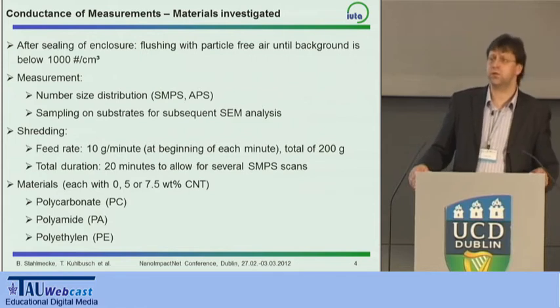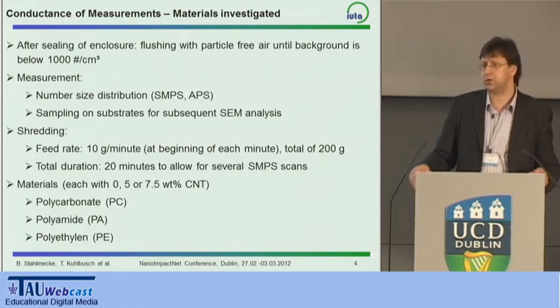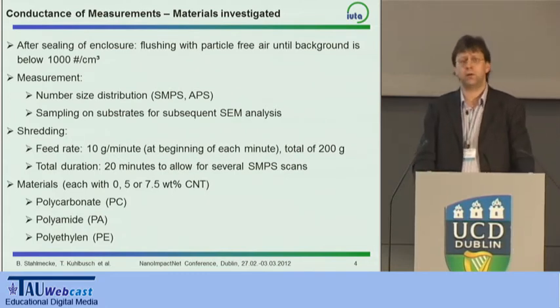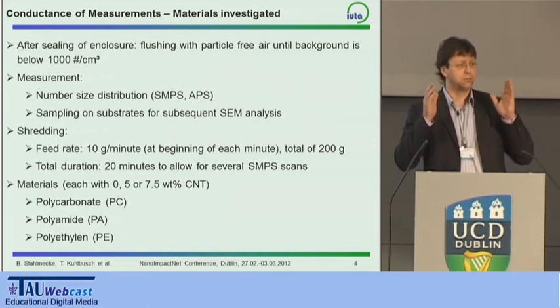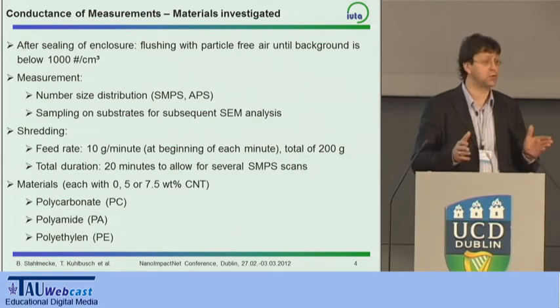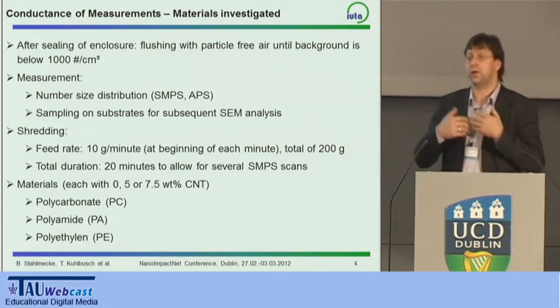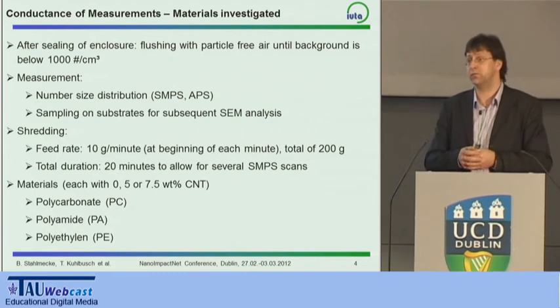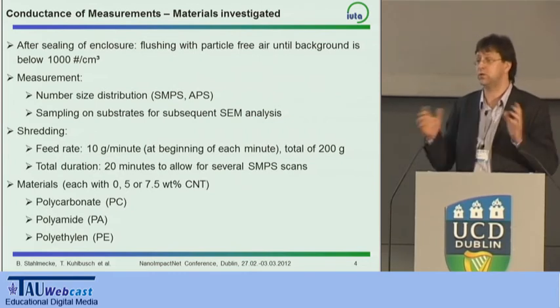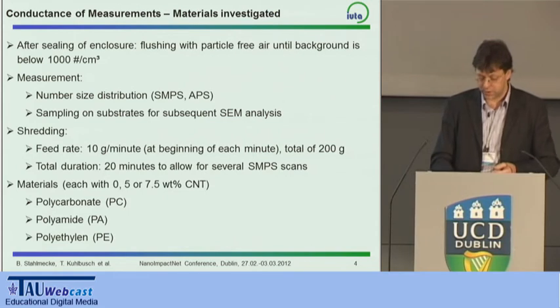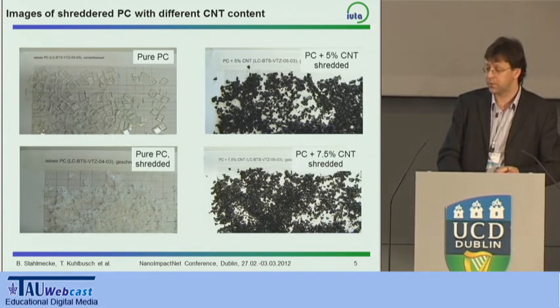The materials we used were 3 different composite materials: polycarbonate, polyamide, and polyethylene. We had them as they are, without any carbon nanotubes added, or we added about 5% or 7.5 weight percent CNT to this composite material prior to the shredding process.